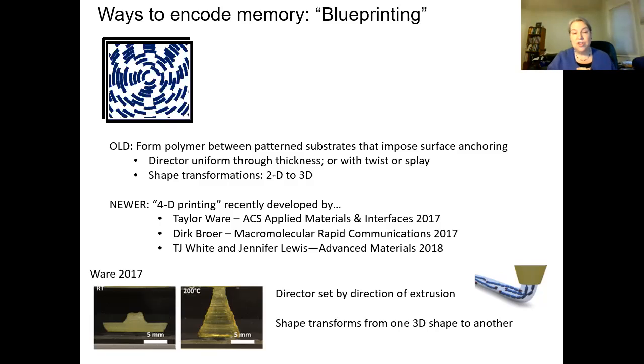And he did something clever. He put two pieces of glass with the coatings on the inside, so essentially an empty liquid crystal cell, and patterned the front and the back at the same time. The advantage of that is if you pattern two separate ones, then you have to try to align them. But if you attach them together and pattern them at the same time, the polarized light can penetrate through the first glass into the second one. Then in particular, you can write a bullseye pattern like this one, or you can write any pattern. In fact, to celebrate Peter Palffy-Muhoray's birthday, they took a picture of him and converted the grayscale picture into an angle and wrote it so they could essentially make a picture of Peter on the liquid crystal elastomer.